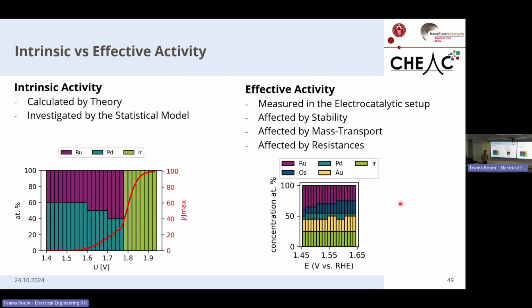So when we are doing calculations, we are looking at the intrinsic activity of the catalyst. And this is the activity of a catalyst under ideal conditions with a very well-defined surface. And this is also the same activity that has been analyzed using the statistical model. But the moment we take our catalyst and we put it in our electrocatalytic setup, we are going to measure the effective activity. So we are going to measure the result of possible surface reconstructions. We will be affected by the stability issues, by mass transport and internal resistances of the setup, and many more.